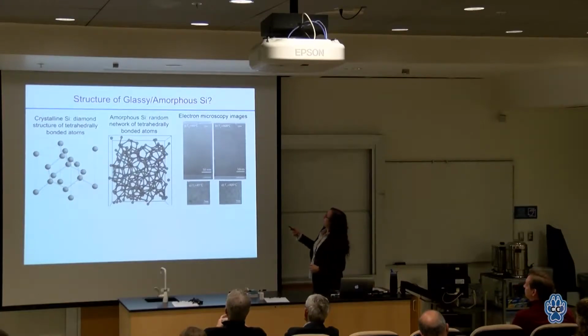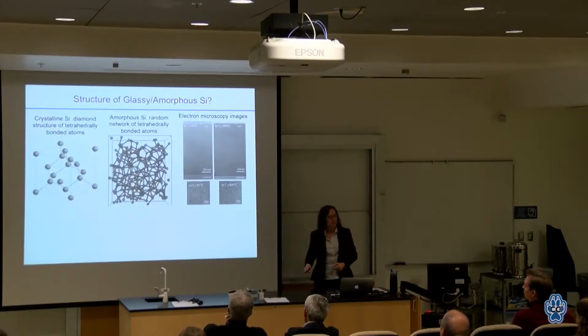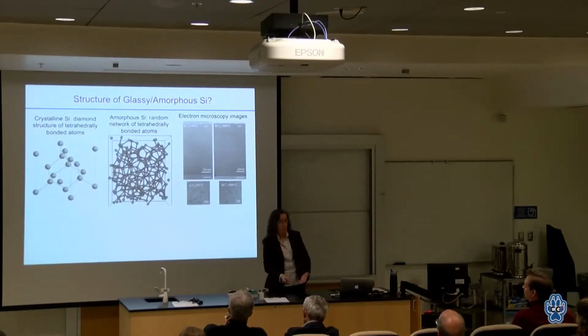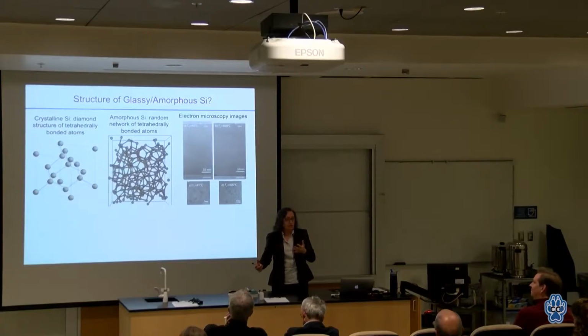Well, these are some electron microscopy images, and let me start with the bottom one. One of my main variables, as I told you, is that I'm going to do vapor deposition, so I'm going to boil the material. I'm going to boil silicon and then condense it onto a substrate. Now, I don't do that in a pot on a stove, obviously. Among other things, it would oxidize. But I do it in an ultra-high vacuum system, and I boil it by shooting an electron beam at it. In the end, I literally have a little pot of silicon, dump a whole ton of electrons in the middle, and it gets hot and melts, and atoms evaporate.